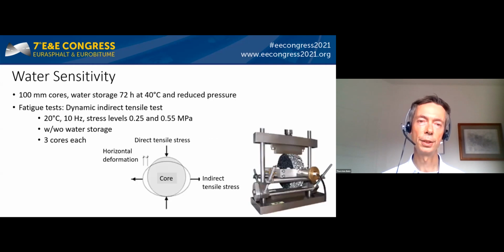For water sensitivity testing, 100 millimeter cores were drilled out of the compacted slabs. 1/2 of the specimens was stored in water for 72 hours at 40 degrees and reduced pressure. Then dynamic indirect tensile tests were performed at 20 degrees with 10 Hertz and 2 different stress levels. 1/2 dry storage and 1/2 with water storage. The diagram and the photograph show the principle and the setup of the test procedure.